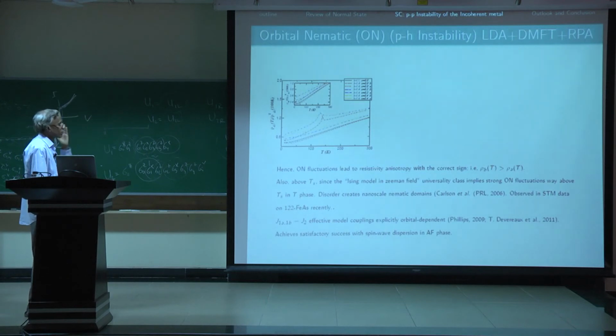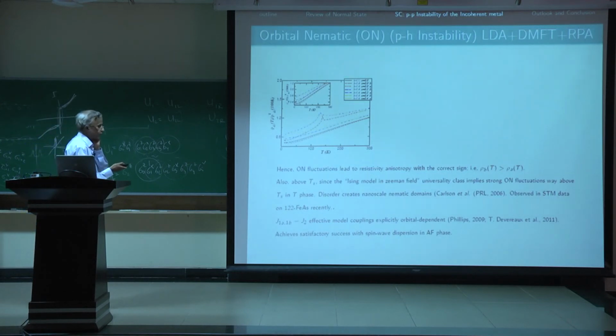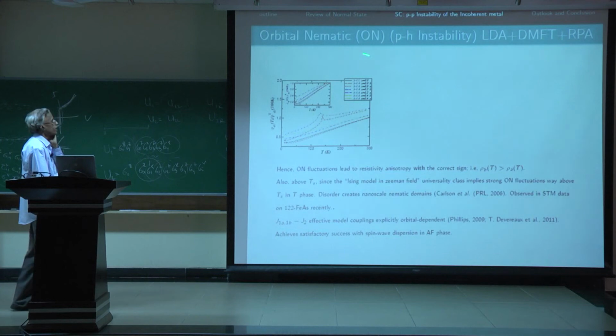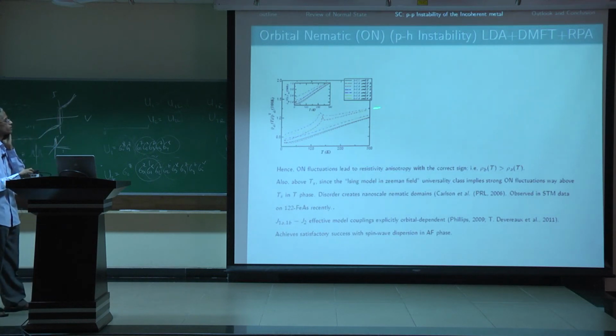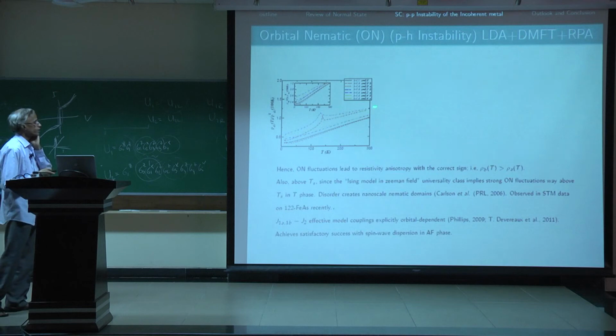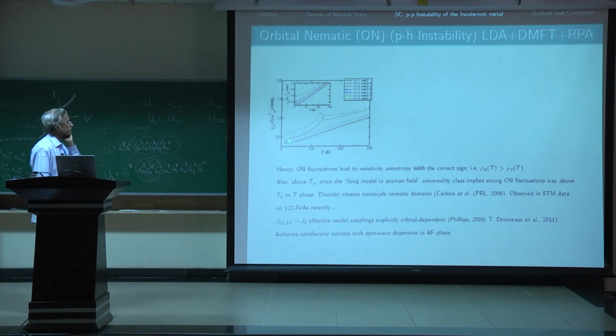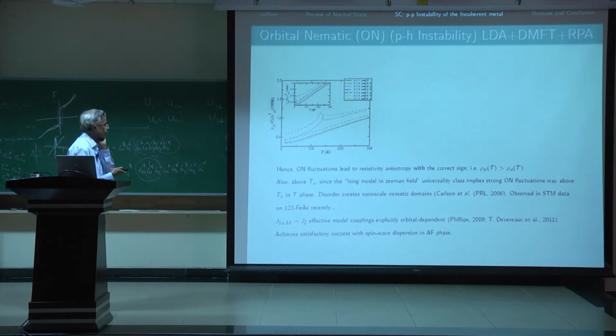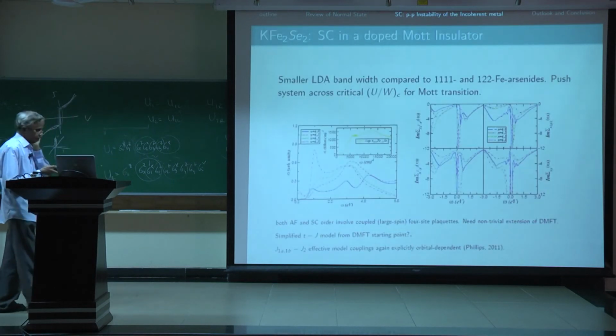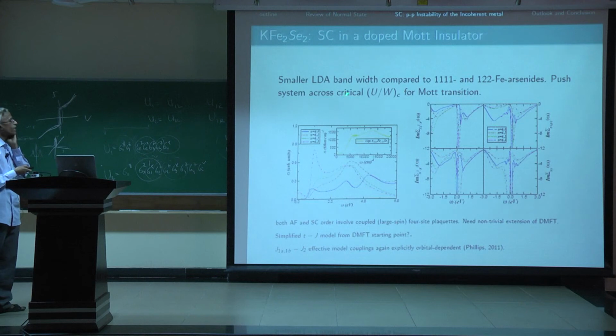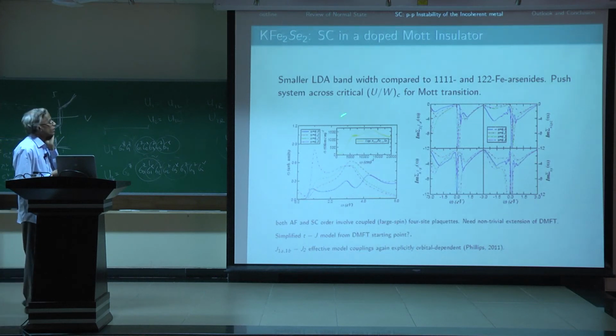Yeah, so this was our earlier attempt, but more recently what we have shown is basically the appearance of a pole in the XZ self-energy basically makes this A-axis resistivity essentially insulator-like in the normal state. And the B-axis resistivity is also basically in the bad metal regime. So you can basically extend this kind of picture to other iron arsenides.